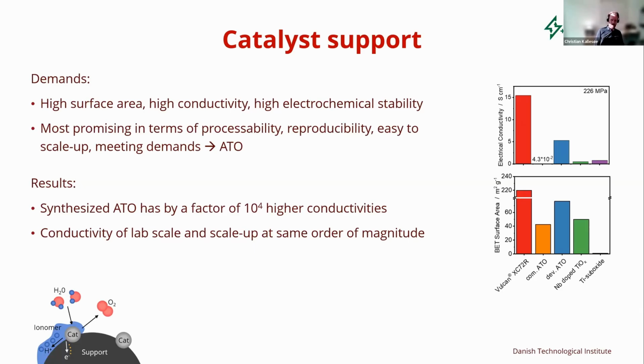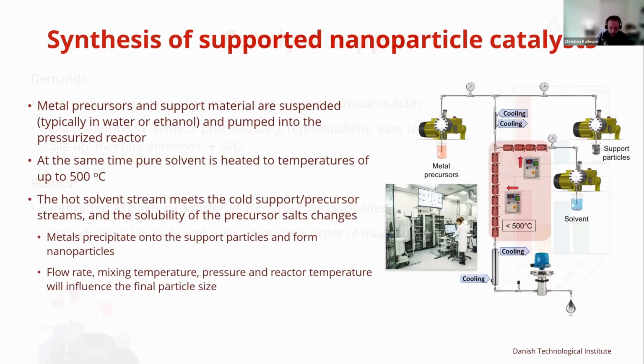Especially when we synthesize it ourselves, we can get high conductivities, not as high as carbon, but in the same vicinity. And we can also get fairly large surface area, again, not as high as carbon, but much higher than all other, both commercial and self-made structures. And that brings us also to the core of our work, where we synthesize particles on these supports. A lot of different particles were tried.